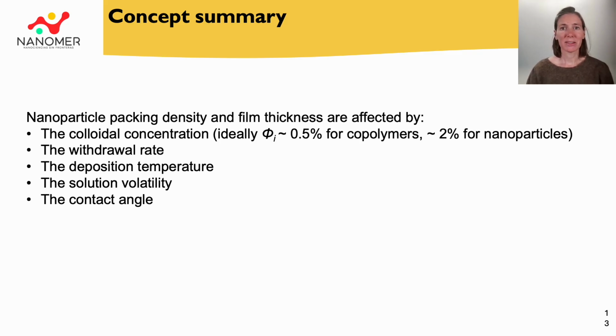We need to think about the withdrawal rate, where thicker films are deposited at very slow and very fast speeds. We have to think about the deposition temperature, the solution volatility, and the contact angle.